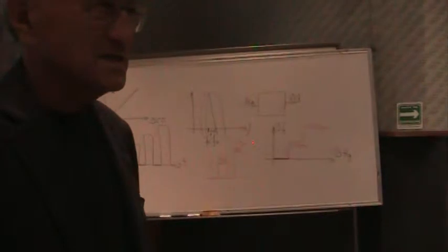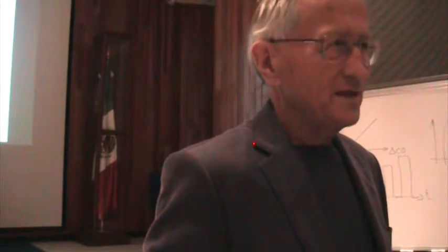But consider the simplicity of this technique. First of all, you have a commercially available element, with no need to fabricate it. In gas sensing, you have a direct frequency output signal. We already know that we are able to measure frequency much more accurately than resistance, voltage or current. And next, we can deposit our nanomaterial-based thin layer on top of this element, and we can measure the concentration of any sort of gas with a proper layer. So you can do this in your own laboratory. It's a very nice approach. Simple and powerful.